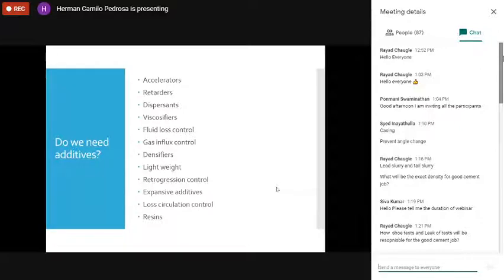Then we have retrogression control additives, which are very important when you're cementing a well that is above 100 degrees Celsius, or 230 degrees Fahrenheit, because after that temperature the chemistry in the cement will be affected, so it will start to break the CSH. So we need some additives to overcome that problem.